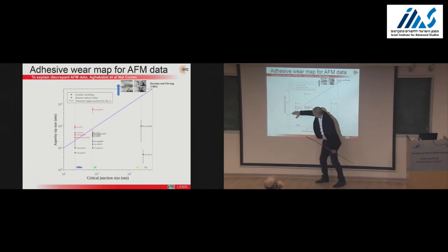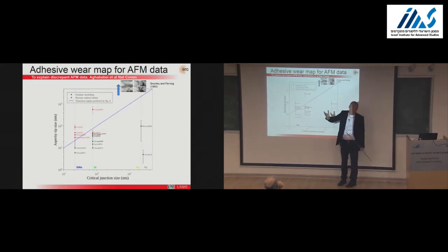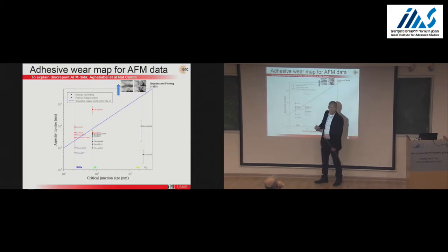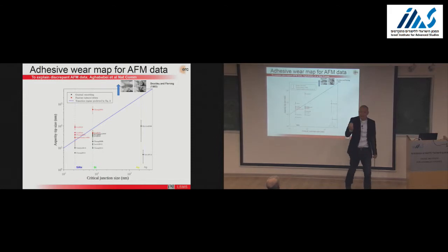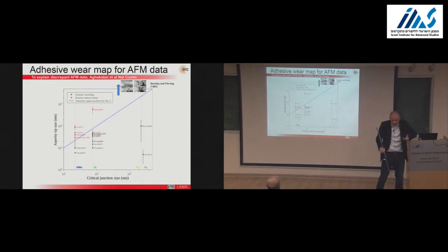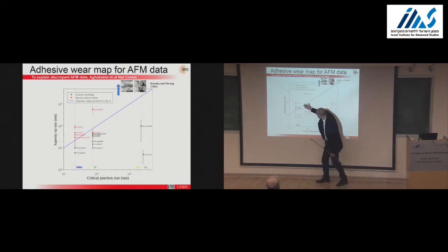This line here is a crossover based on the critical length scale estimate, from below this line, what should be smooth wear, to debris formation. And you see data points that are in red. We chose the color red to portray those data that did generate debris. And the black points show smooth plastic wear. So it's roughly consistent with the predictions.